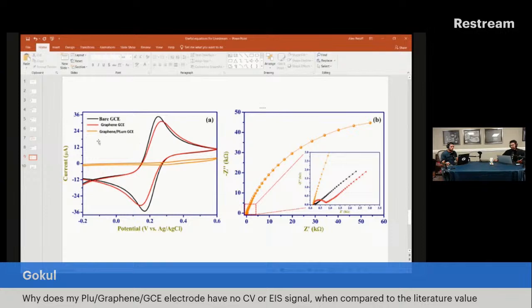And when he makes this graphene PLU mixture, so to say, on the glassy carbon electrode, we can see that he gets no signal in the CV. There's very little to no electrochemical response that we're observing.